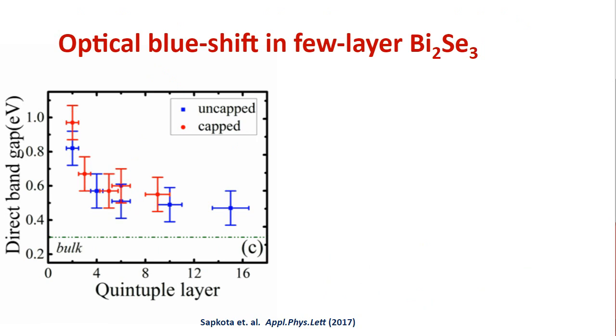And then we essentially plotted all sorts of samples that we had, both the capped and uncapped, and plotted the band gap estimation as a function of the layer number. And you can see a very nice trend irrespective of the capping and uncapping. We can clearly see that as we reduce the thickness, the band gap is increasing, right? It starts off at around 0.5, like we were showing for 6 layer, and that persists even up to as high as 16 layer. But as we go below 6, to 4, 3, 2, 2 is almost 0.8 eV or higher, right? So this was a new thing that we were seeing. So clearly we see a strong optical blue shift in few layer bismuth selenide.